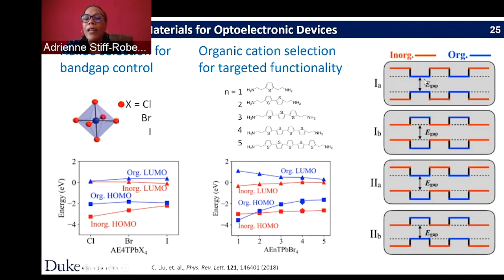So you could have a type 1 lineup where recombination would happen across the organic. You could have a type 1 lineup where recombination happens across the inorganic. Or you could have type 2 lineups where you'd expect to see recombination suppressed because you're actually separating electrons and holes across these two different materials. So this had been predicted. This was expected to happen from early work that David Mitzi had done, but they were not able to demonstrate this for the wide range of organic molecules because they couldn't synthesize the films.